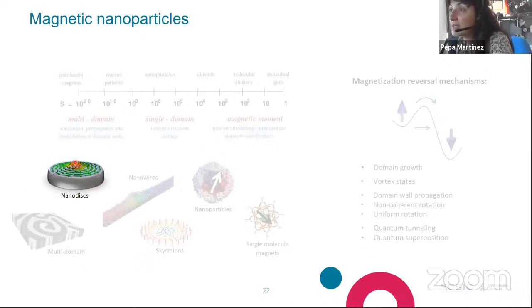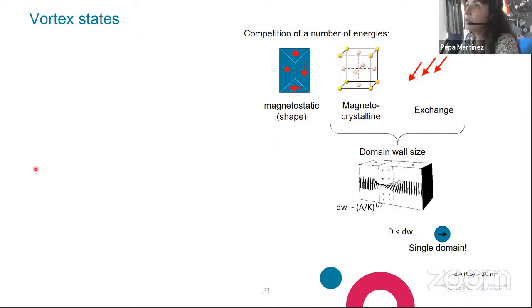Let's start with nanodiscs. So almost two-dimensional objects with some boundaries, okay? Before doing so, let me introduce you to what a magnetic vortex state is. In conventional bulk magnetic materials, the resulting ground state, the state of the object, will be given by the competition of a number of energies. You have on the one side the magnetocrystalline and exchange energy that tends to align magnetic moments parallel. In the case of magnetocrystalline anisotropy, parallel to some preferred axes, and in the case of exchange, parallel between them, for instance, for the case of a ferromagnet.